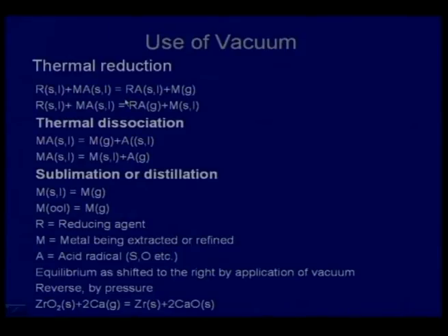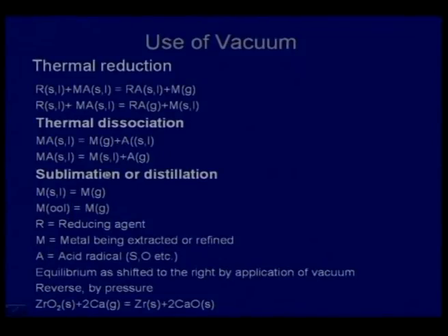We can apply vacuum and help the reaction go forward. So, many pyrometallurgical operations make use of vacuum. Of course, it will be true for sublimation or distillation also. Like if you have a metal, we want to purify it, and if we heat it, it forms a gas.